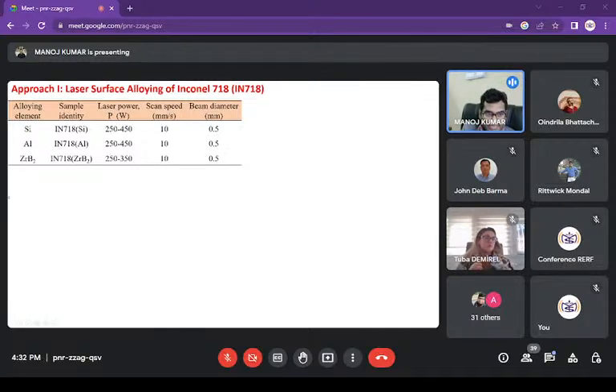They are again very good candidates for high temperature protection. Interestingly, we also tried with ZrB2, and it gives very different results. It started forming some borides and some complex zirconates. Those are also stable at high temperature, but in the end we realized that silicon gives the best protection, followed by aluminum and then ZrB2.